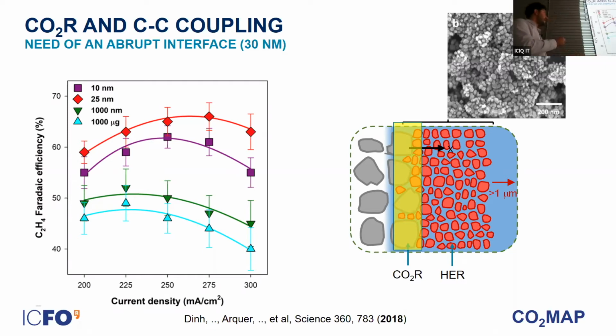You can see here how the Faraday efficiency for ethylene compares versus current density for different thicknesses. And you can see that the highest performance is achieved for 25 nanometers. And you can see how by increasing the thickness of the catalyst, by increasing the catalyst loading, which in principle would allow you to achieve high productivities, is actually decreasing performance. So that's why it's important to have a very abrupt catalyst in these reaction conditions.